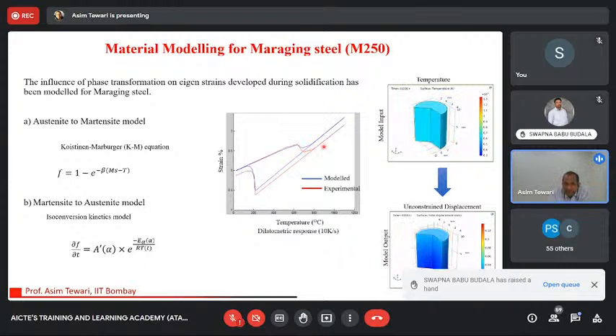Then of course, if you keep heating it up again, the newly formed phase of austenite goes through thermal expansion, leading to this. So this is the heating cycle. Now the cooling cycle is more interesting, because now you are cooling and you have austenite, so it goes through a cooling cycle because of thermal contraction, but it does not form martensite right away. At the temperature at which the martensite changed to austenite, you don't form martensite when you're cooling, and there's a hysteresis involved in this. That hysteresis means that you will have austenite down to a lower temperature, almost 200 degrees C, and after that you suddenly will form martensite. And as you form martensite, which has a lower density, it will expand. So suddenly you'll have a strain increase.